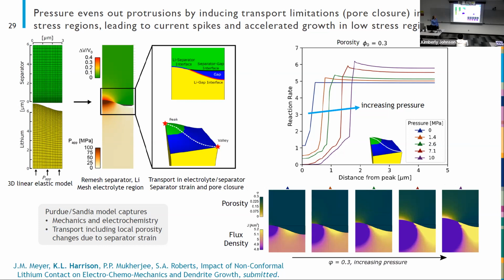So this plot on the upper right is showing the reaction rate at the surface along that sort of diagonal between the peak and the valley. And what we see is that the reaction rate drops to 0 when we have high pressure. And that's because pores close in the separator. We're no longer able to transport lithium ions to the surface in that location. So we can't have current and reaction of lithium there.